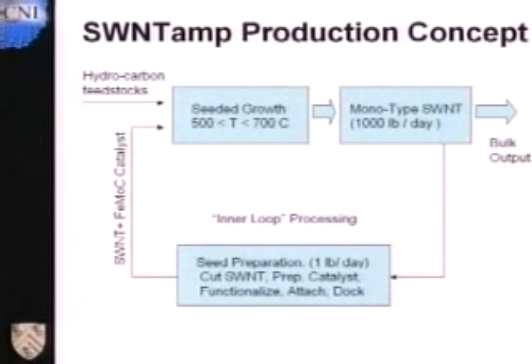We hope this can be scaled up to a commercial process at large scale eventually, and this would be what that kind of process would look like industrially, where you have a standard growth chamber where you're using seeds instead of promiscuously letting the seeds generate themselves. And say you're putting out 1,000 pounds a day, you then take about a pound out, and then do that cutting process, add the catalyst, and put it back into the reactor. And so we think that we can get gains in here on the order of 1,000, perhaps more, perhaps a bit less. But this is what we call the SWNT amplifier.